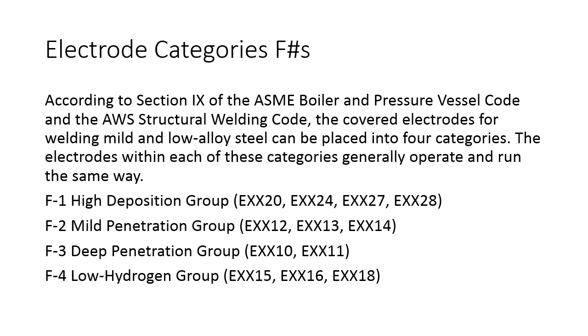We're talking about 6010 and 7018 today, so the 6010 would be in that F3 group. It's also in there with 6011. Those materials have a lot of, like I've stated and will state, cellulose in the flux, organic materials. They're a fast freeze electrode. So they run pretty well uphill and in out of position welds because it's a fast freeze material.